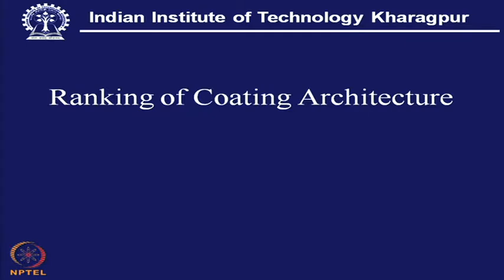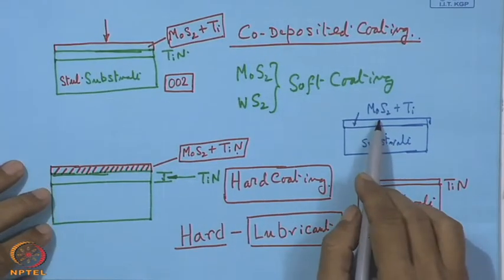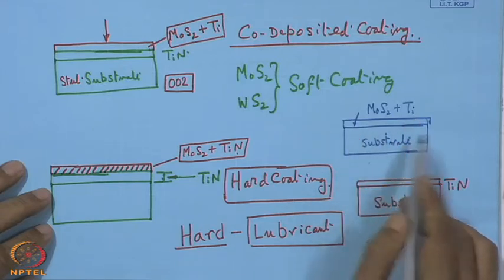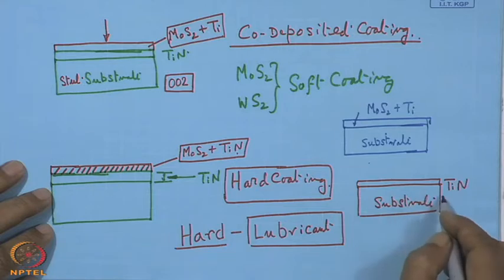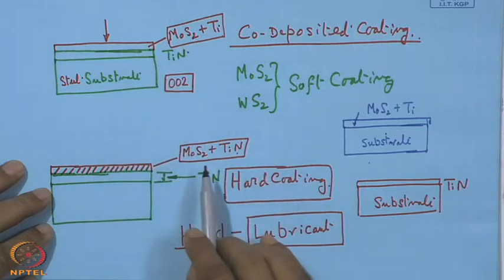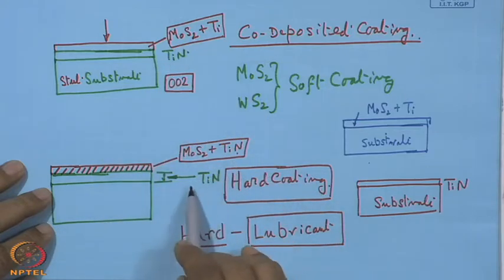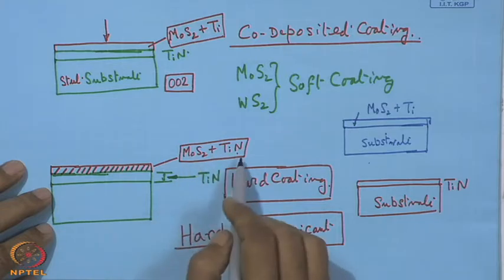Now, the question is, these are the architectures. Now, how can we rank this coating architecture? For ranking this coating architecture, we have to find out some ways or means. That means, this coating has to undergo some kind of characterization, and it is going to be a mechanical sort of characterization. That means, the coatings whatever we have mentioned here: just molybdenum disulfide without any support of TiN, a conventional hard coating TiN, and MoS2 with TiN support, and this is a composite coating.